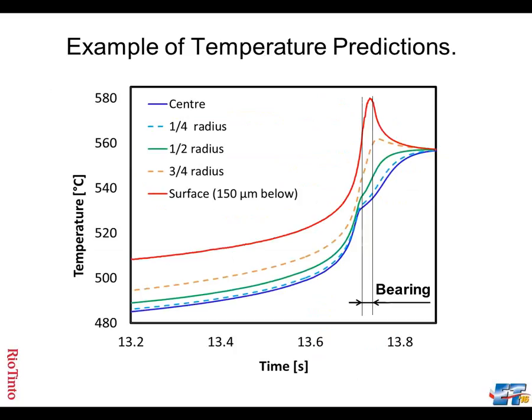And this is the kind of information you get. This shows the temperature with time for the center of this bar and the surface of the bar, and you can see the red plot above is the hottest. The bearing is running a lot hotter than the core of the aperture, the core of the die. You can see, for example, that the surface temperature in this case is 580 Celsius, whereas the metal running through the center of this bar is 520, substantially cooler.